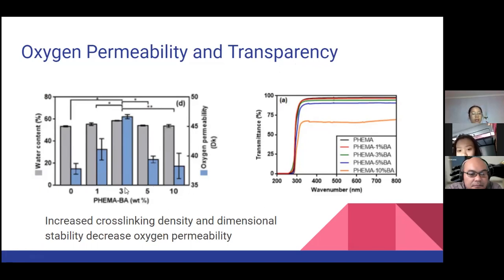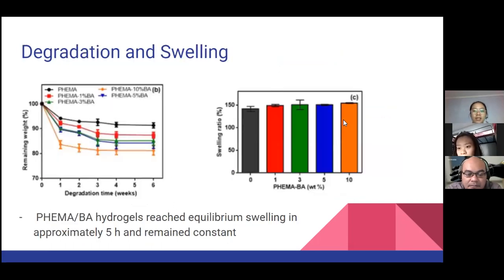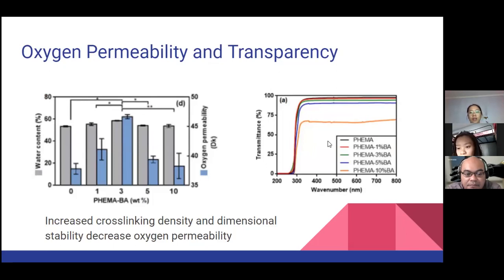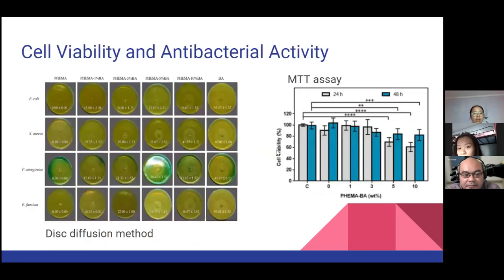Why? The researchers said that because the increased cross-linking density inside the hydrogel increased the dimensional stability, it decreased the oxygen permeability because it is already packed up inside the hydrogel. As for the transparency, the higher the concentration of boric acid, the lower it can transmit light. Next is the cell viability and antibacterial activity.